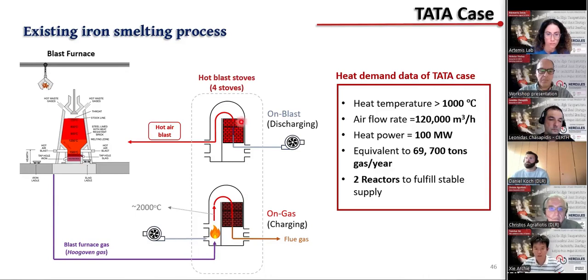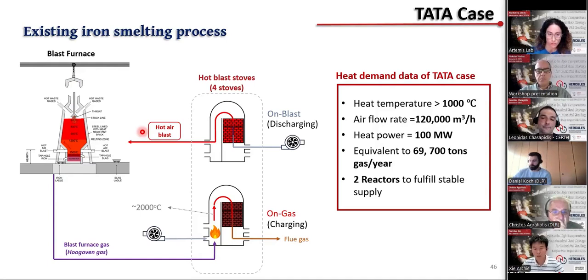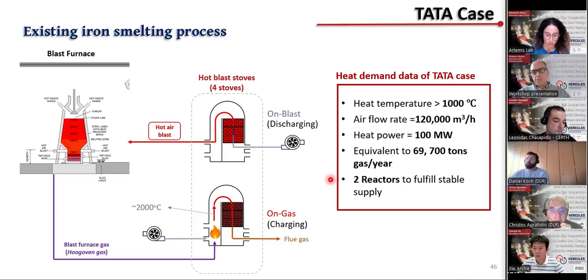And in the discharging process, the bricks will heat the air flow in and then provide the hot air to the furnace. In the actual process, there are 4 stoves to ensure the stable energy supply for the iron smelting, while in this diagram, we only show 2 of them to explain how it works. For Tata Steel, they need the hot air temperature over 1000 degrees C at a very high flow rate, and the heating power is around 100 megawatt. In the system simulation we have done, we use 2 HERCULES reactors to fulfill the energy supply of Tata Steel. Next slide.